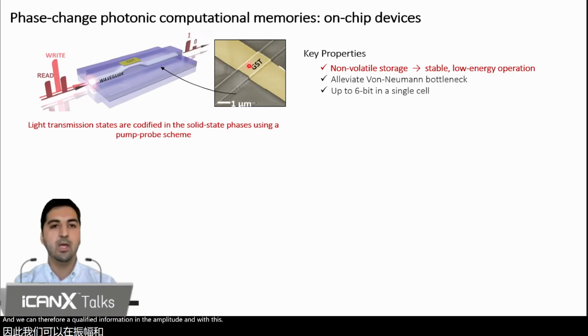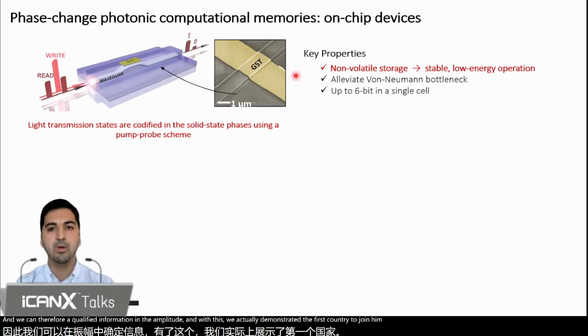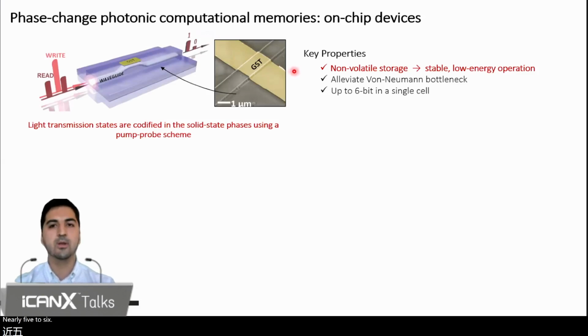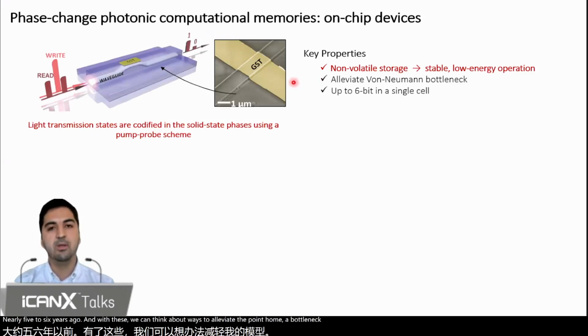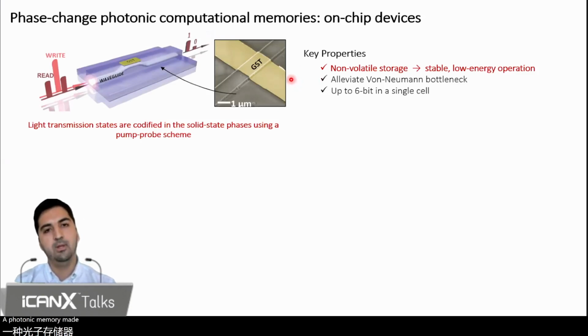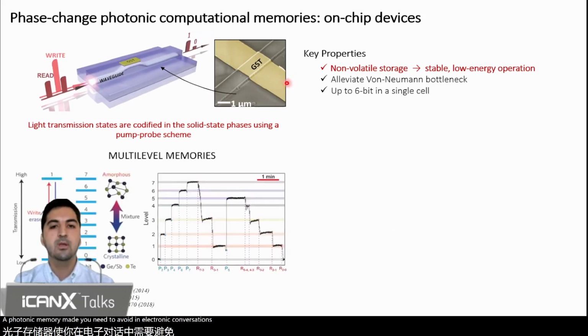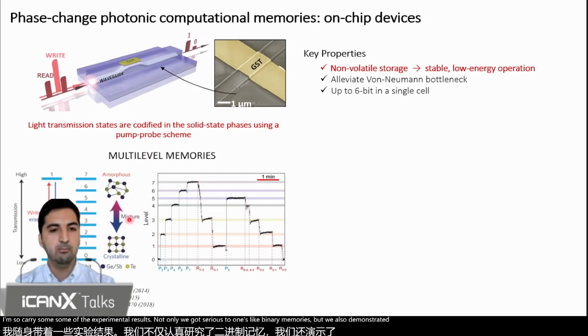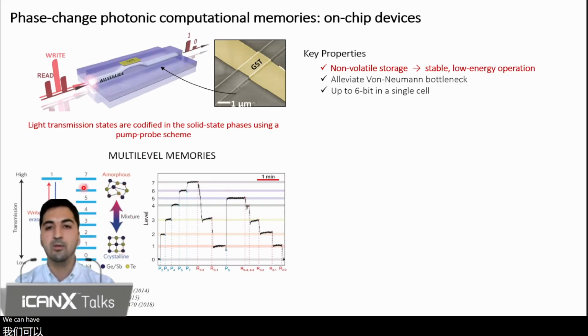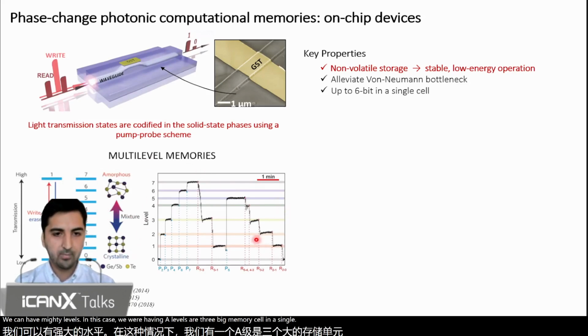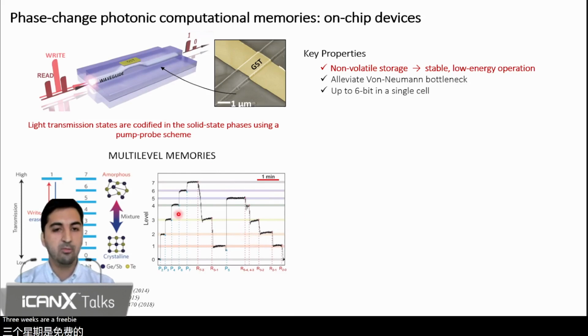And with this, we actually demonstrated the first on-chip photonic memory nearly 5 to 6 years ago. And with this, we can think about ways to alleviate the von Neumann bottleneck, because having a photonic memory might lead to avoiding electro-optical conversions. So here are some of the experimental results. Not only did we get zeros and ones like binary memories, but we also demonstrated that by controlling the mixture of material between the crystalline and amorphous, we can have multiple levels. In this case, we are having 8 levels, 3-bit levels in a single memory cell.